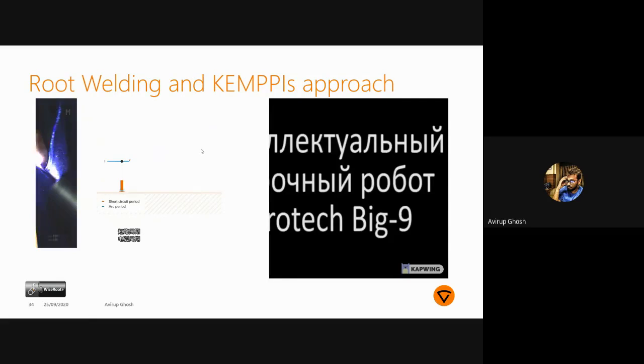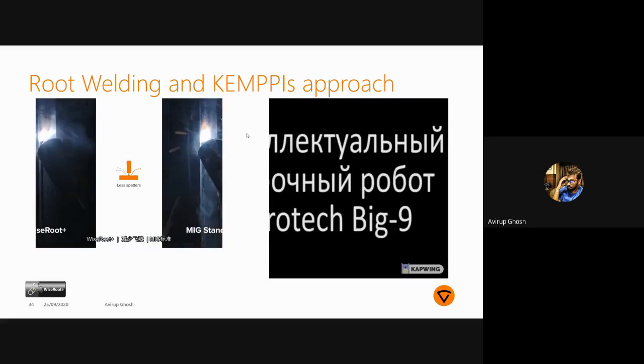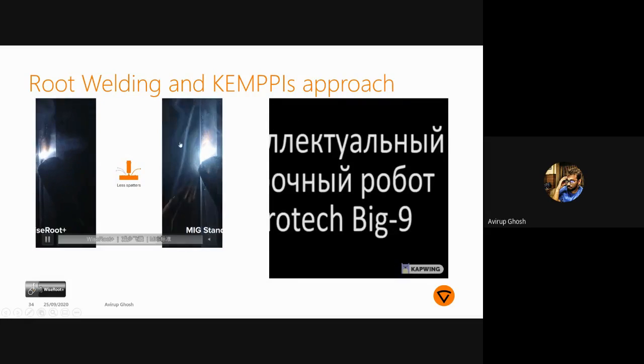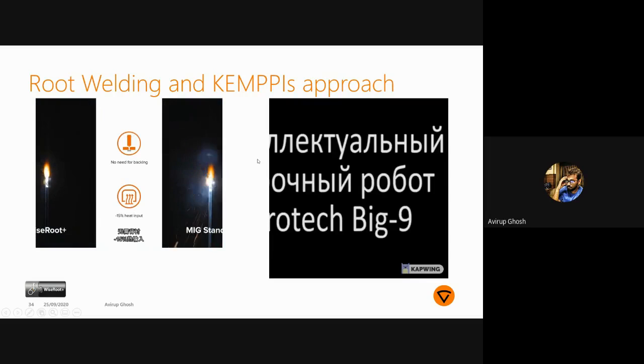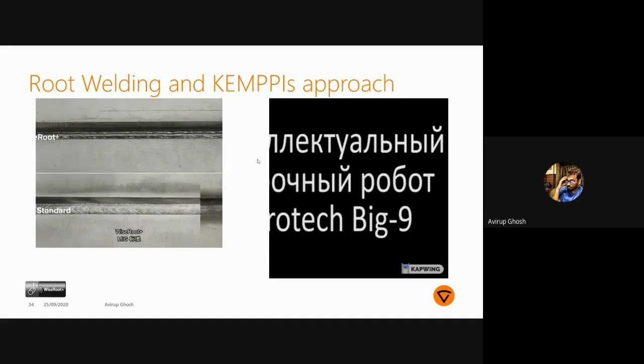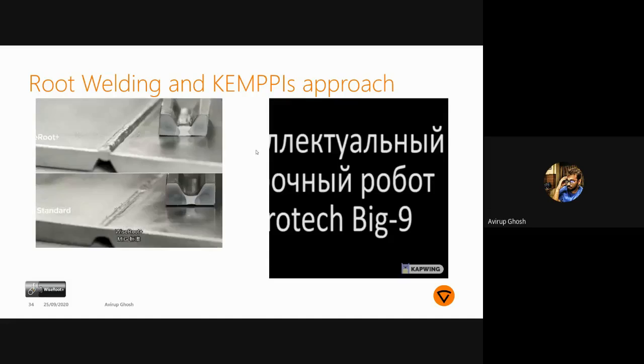So as you can see, the torch angle is continuously changing from 1G to 3G to 6G, and even overhead positions. We have done this process even in overhead positions without any change of parameters, and we can achieve uniform beads, uniform root welds. This is a mixed process where it shifts from short arc to globular transfer, comes back to short arc and again globular transfer. This is totally done from the power source itself without changing any parameters.